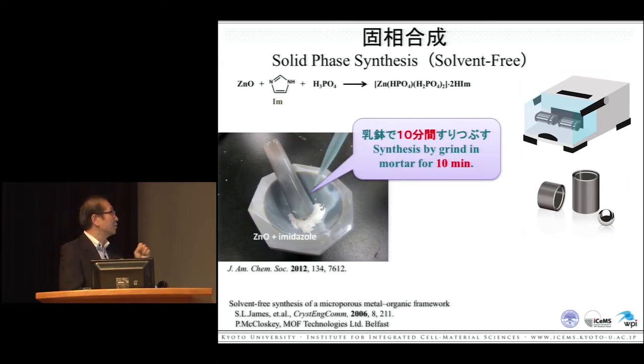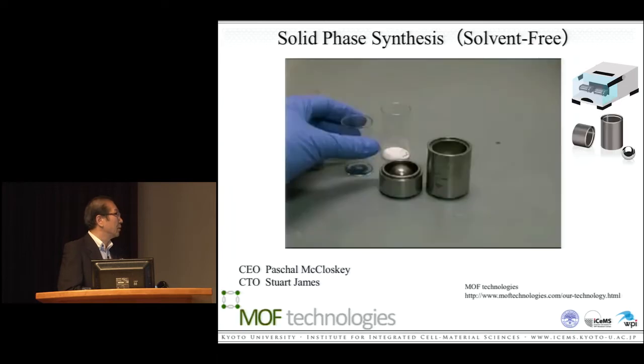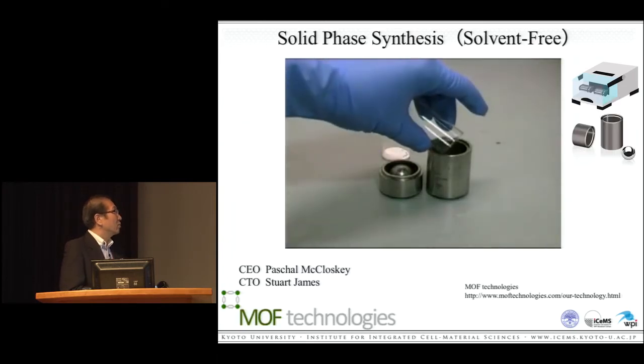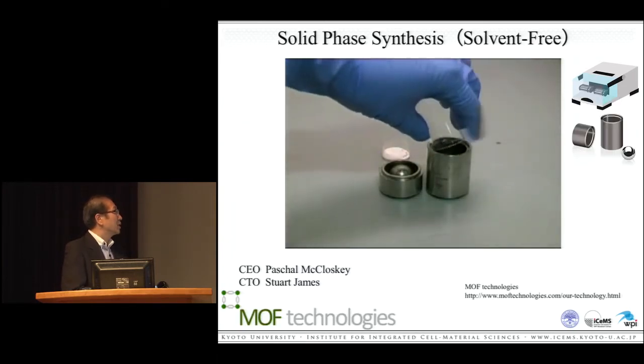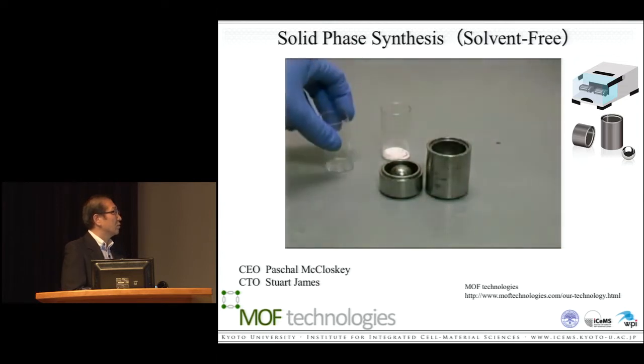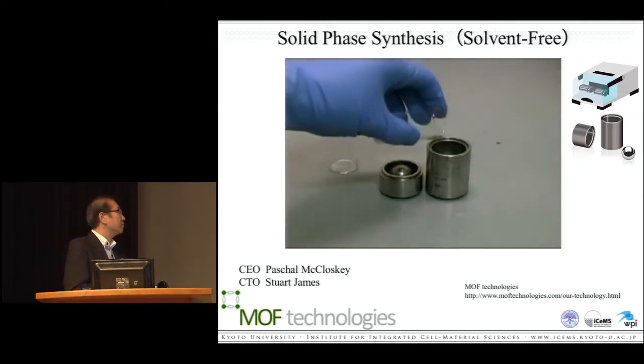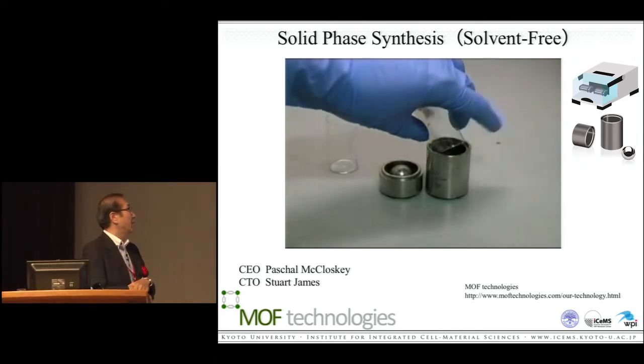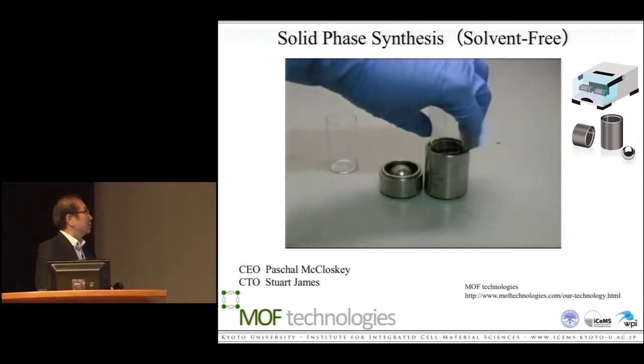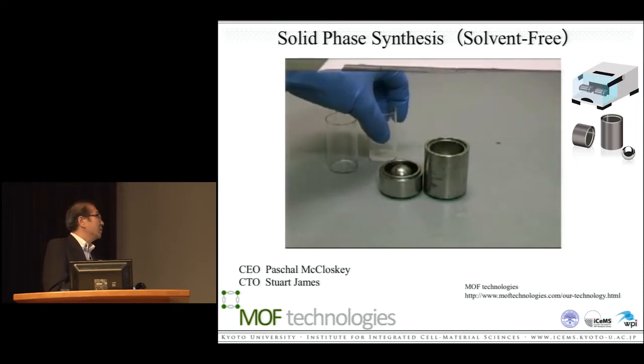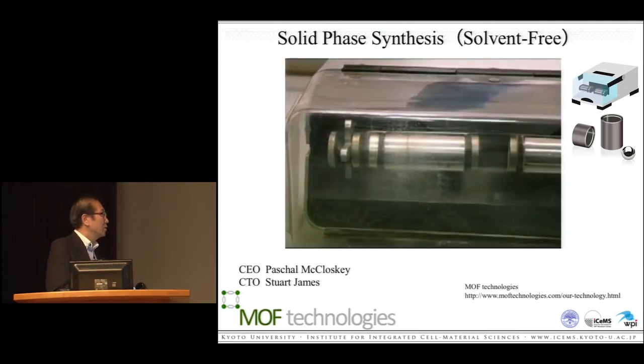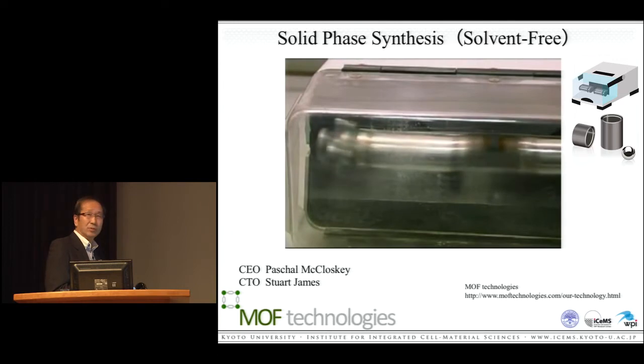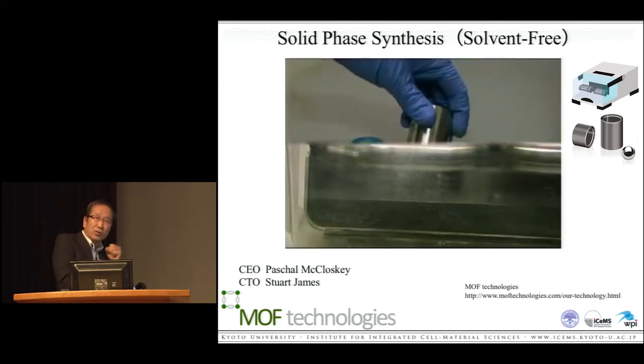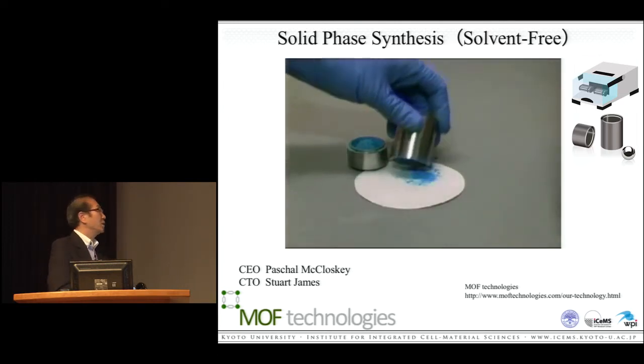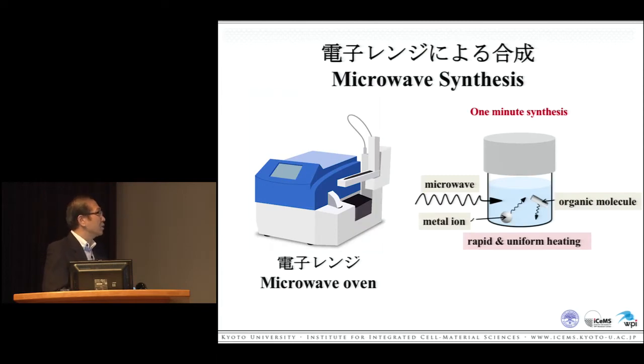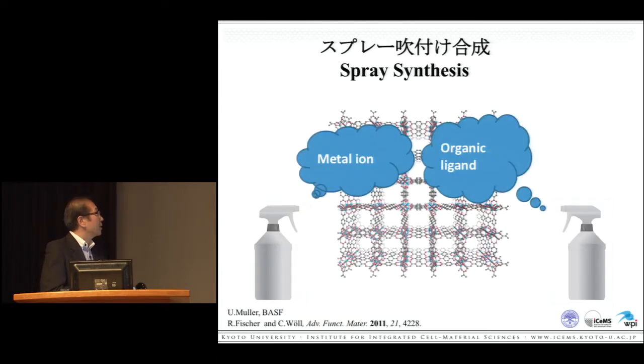An easier way is to use a mortar for grinding for 10 minutes. It may be too hard for your hand, then you can use a metal ball for shaking. MOF Technology is a company which discloses this technique. We also use the same methodology. A short time of shaking would be the same as grinding with a mortar. Or with a microwave, since this is possible, you need only 1 minute.